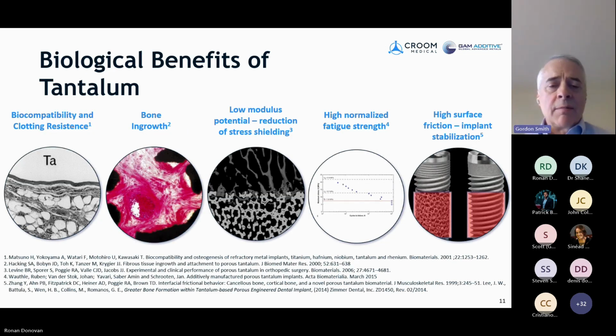Now we can expand further on what makes tantalum an ideal material for implanted medical devices that interface with bone. If you're looking into the literature, tantalum is an ideal material for implantable medical devices due to demonstrated biocompatibility with resistance to blood clot formation, enhanced bone ingrowth, low modulus, high normalized fatigue strength, and high surface friction. With respect to blood clots, thrombus formation post-device implantation is a real risk and can lead to strokes, heart attacks, and even death in some cases. Indications in the literature, you'll find tantalum helps prevent this side effect due to resistance of blood clot formation.